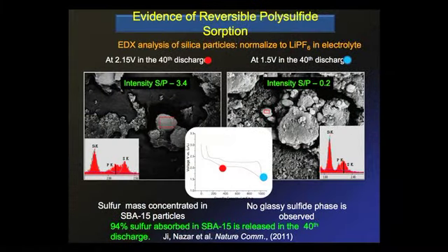What we did to prove this was we carried out SEM and EDAX measurements of the materials, either at this point, which is the maximum polysulfide concentration, or at this point at full discharge. In the results shown here, where we analyze one of these SBA15 particles, we see a high sulfur concentration. We reference to phosphorus because our electrolyte is LiPF6, and it's everywhere, so it's a normalizing factor. At this point, we have a sulfur to phosphorus ratio of 3.4, whereas at full discharge it is only 0.2. This just shows the EDAX data, and we are analyzing, again, an SBA15 particle.